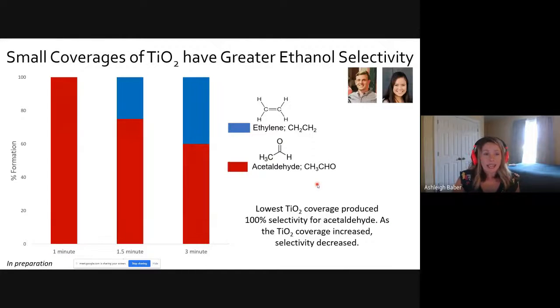Okay, so this indicates that coverage makes a difference. If we deposit titania for 1 minute onto our surface versus a minute and a half versus 3 minutes, the longer we deposit titania, the more we have and the less selectivity we are able to see between ethylene and acetaldehyde.